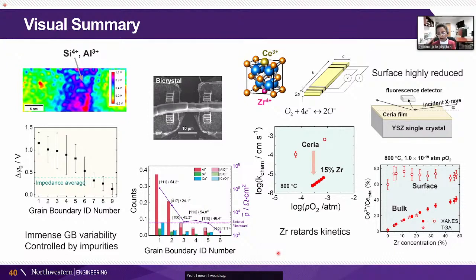Yeah, I would say that part is actually still open. What I didn't tell you is that we do our XANES measurement, and we basically analyze the spectrum by doing linear combination fitting, which gives us big error bars, big uncertainties, and you get the overall shape of the spectrum. What we did notice between the 3 different orientations was that the intensities were slightly different. And I've heard it argued that reflects a level of covalency in the bonding, even though the oxidation state might be globally the same. And so that's still a point of interest for me. And certainly the electronic transport, in the zirconium-doped system, it's very much an electronic conductor as opposed to an oxygen ion conductor.